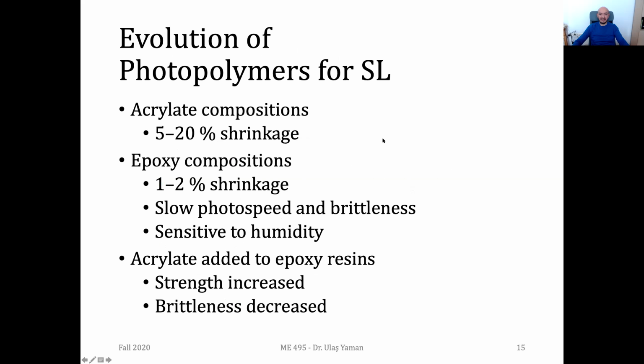So what do we have inside these photopolymers? In the earlier days, while people were trying to invent such photopolymers, they simply used acrylate type compositions. And the problem with those compositions was a huge amount of shrinkage. Sometimes if you purely use acrylate compositions, we may have up to 20% shrinkage, which means that if you have a 10 centimeter part, then after curing and all operations, its size might decrease to 8 centimeters. And then they started to use just epoxy compositions.